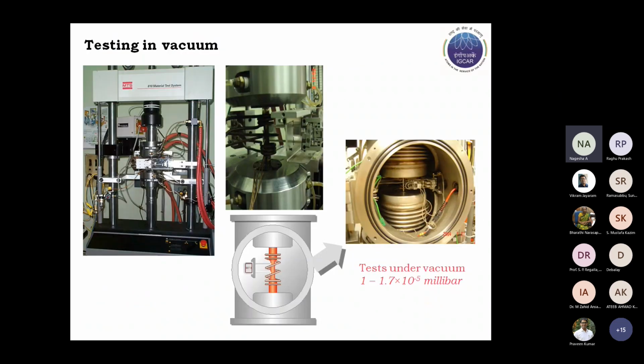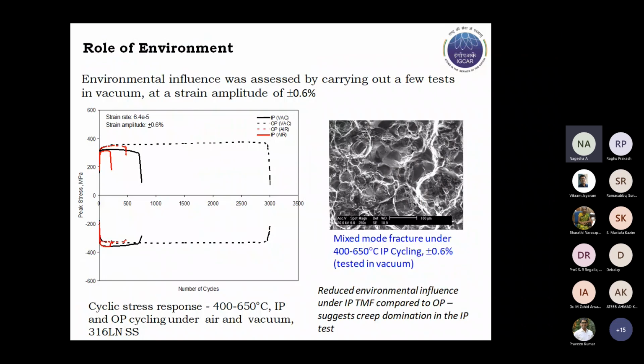And a few tests were carried out in order to examine the influence of environment. Few tests were also carried out in vacuum. So this is the kind of setup that was employed for vacuum testing, and a few tests were carried out at a strain amplitude of 0.6%.